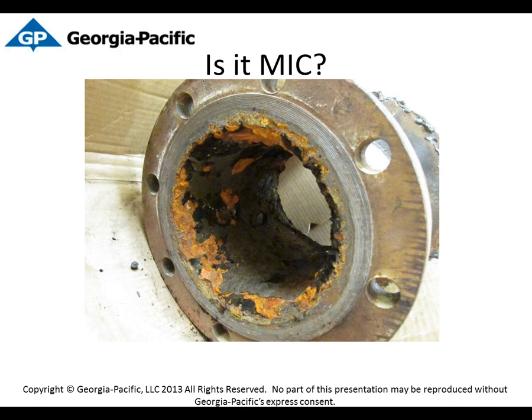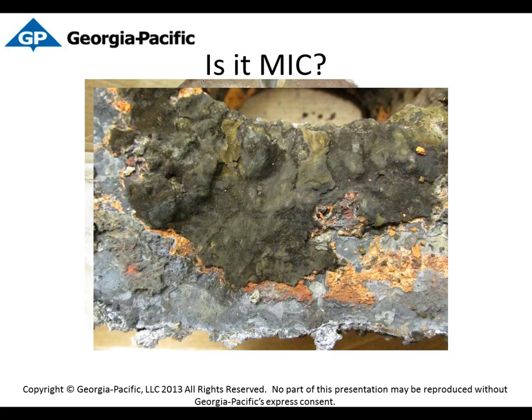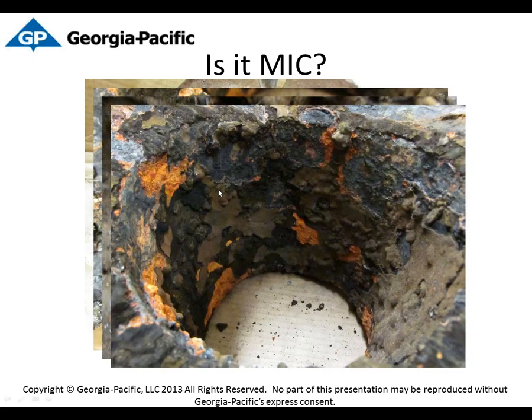So then as we learned more about it, we started looking for it in other mills. This is a sample that came from another southeastern mill, and when we first got it, to the average person, you look at this and say, well, this is going to be under-deposit corrosion. That's pretty typical. Just inorganics and organics in the water caking up on the pipe wall, causing corrosion. And we said, well, does MIC play a role in this? And most people said no. We said, well, possibly. What about slime formers or anything else? Bacteria that form on the wall actually create the surface conditions to allow inorganics to adhere to the wall.